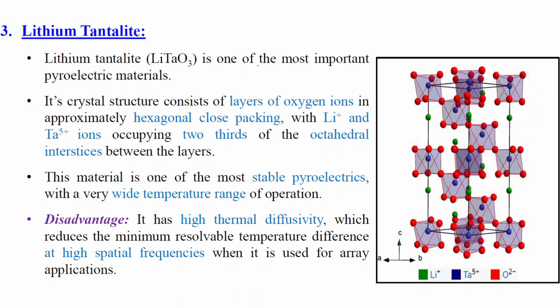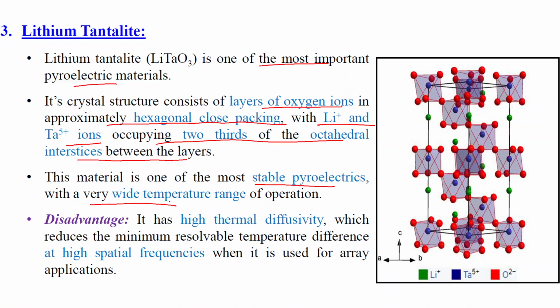Lithium tantalate. Lithium tantalate is one of the most important pyroelectric materials. Its crystal structure consists of layers of oxygen ions, approximately hexagonal close packing, with lithium and tantalum ions occupying two-thirds of the octahedral interstices between the layers. This material is one of the most stable pyroelectrics with a very wide temperature range of operation. The disadvantage is that it has high thermal diffusivity, which reduces the minimum resolvable temperature difference at high spatial frequencies when it is used for array applications.